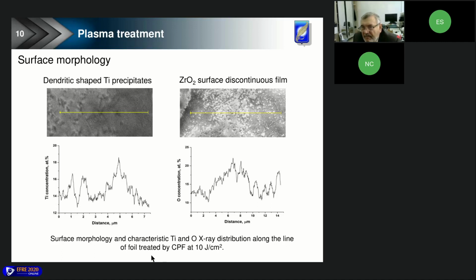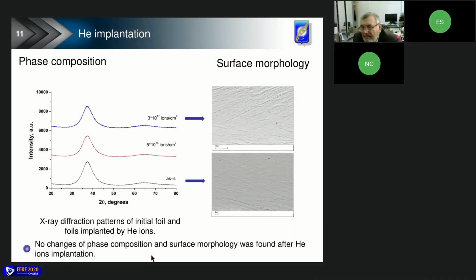Well, you have seen that plasma treatment under the used parameters resulted in the crystallization of the foil, at least its surface layer. So the cooling rate of the plasma impact was lower than the critical rate necessary to preserve amorphous structure. Its value should be in the range of 10^4 to 10^6 Kelvin per second. The question appears on the stability of the materials to helium radiation, in particular on the resistance to blister formation.